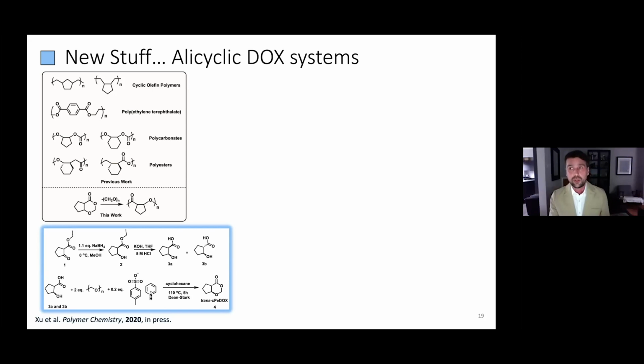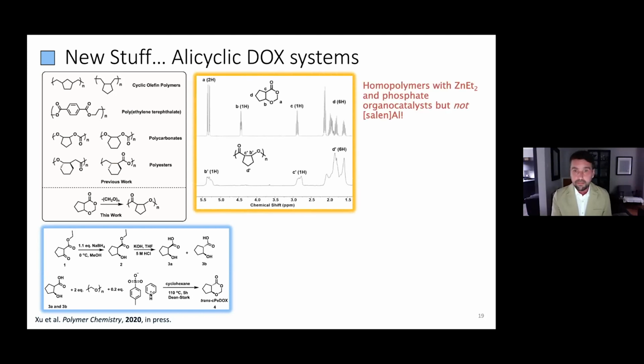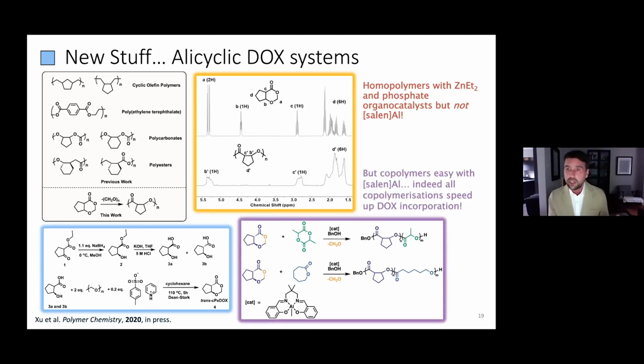So we have a selectivity in terms of the control from a tacticity perspective, simply by the energetics of the actual ring opening step. And interestingly, we see very different behavior if we think of this as a homopolymer candidate versus a copolymer candidate. For homopolymers, we have to use quite an aggressive catalyst with diethyl zinc or other zinc salts to be able to facilitate this. We see no polymerization with our traditional aluminum salen system. But interestingly, we do get incorporation and, in fact, an increase in speed of those reactions when we do a copolymerization. This is again showing the importance of understanding the kinetics of these reactions, as this is all down to reactivity ratios between our two monomers.